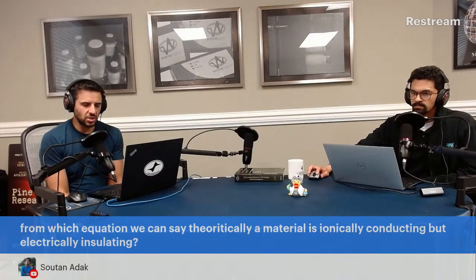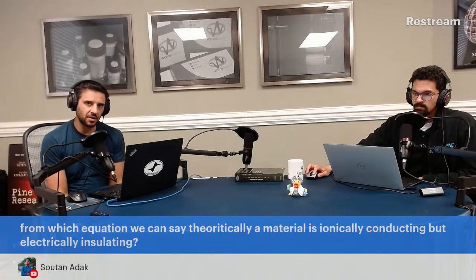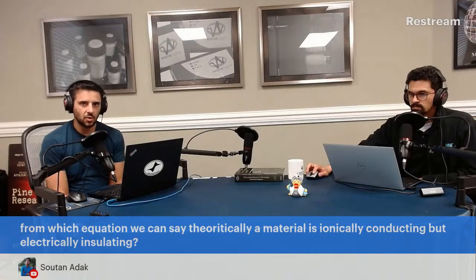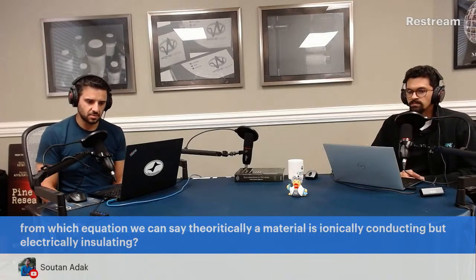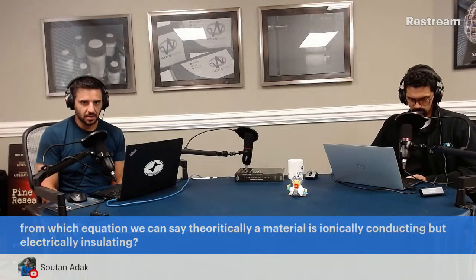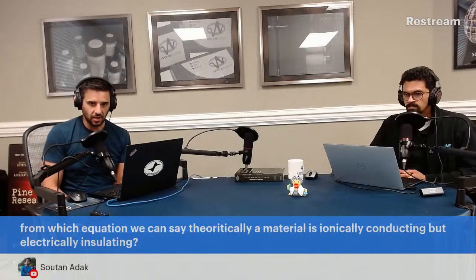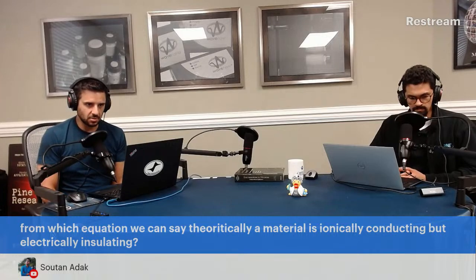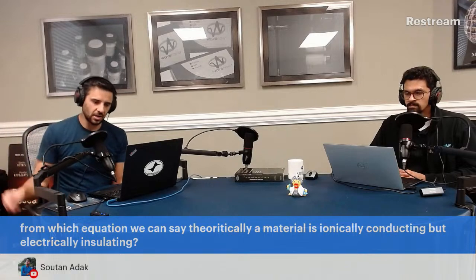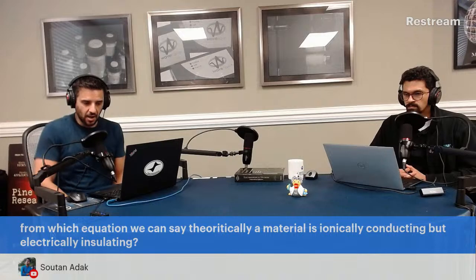Most commonly, the equation that people use is L over RA. So, for instance, for the ionic conductivity of a membrane, you do a 4-point probe technique. You have a surface area exposed, you have a distance between the two electrodes, and that's L. A is the surface area, and you get a measure of the resistance either through impedance or a very slow linear sweep voltammetry. You use Ohm's law and you get the resistance, and then you get a length unit in there, so it's Siemens per centimeter, L over RA. And that's ionic conductivity.